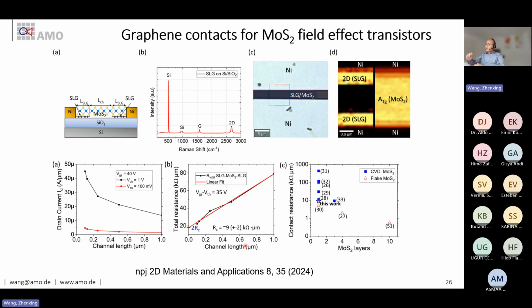So of course, there is another material called MoS2. It's even more difficult to make a good electric contact to these materials because of the Fermi level pinning and so on. So we were thinking maybe it's easier to make contact through graphene because of the van der Waals stacking between the graphene and the MoS2. So we try to contact MoS2 with graphene, single layer graphene here, SLG, and then contact graphene with nickel. By doing that, indeed, we can also improve the contact resistance. It's rather low, you see.